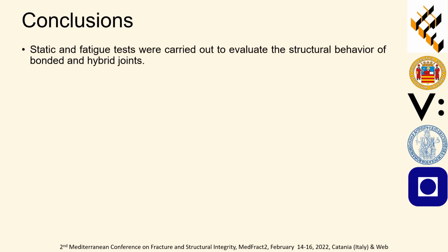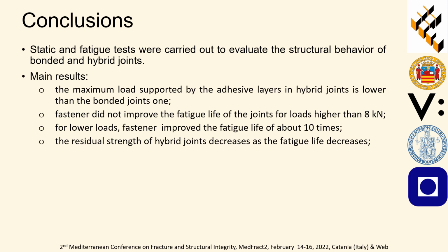So, in conclusion, we can say that in this research activity, we performed static and fatigue tests to evaluate the behavior of both bonded and hybrid joints. In particular, we can summarize the results, and we can say that the maximum load supported by the adhesive layer in hybrid joint was found to be lower than the one supported in bonded joint. Moreover, it was also found that the presence of the fastener didn't improve the fatigue life for higher loads, whilst in contrast, for lower loads, the fastener has an influence on the fatigue life, and it improves the fatigue life by about 10 times. In conclusion, we can also say that the residual strength of hybrid joints decreases as the fatigue life decreases.